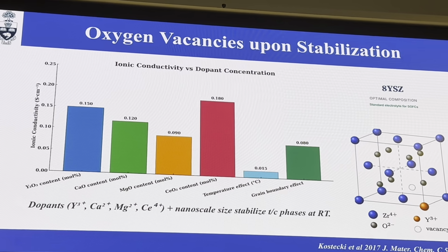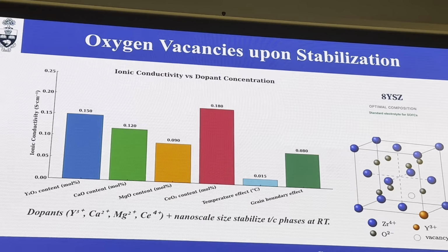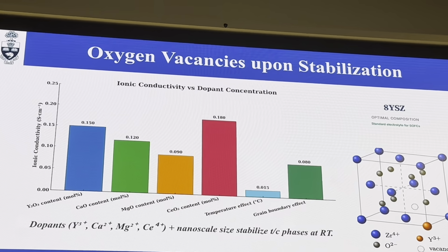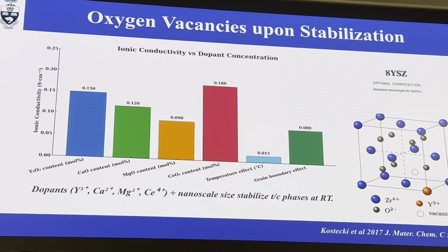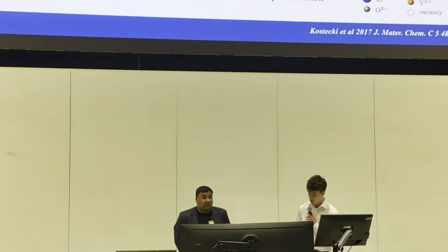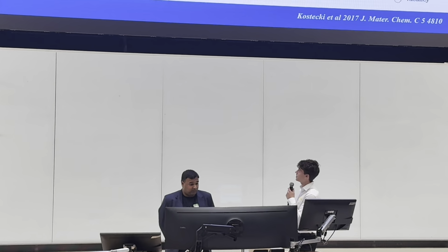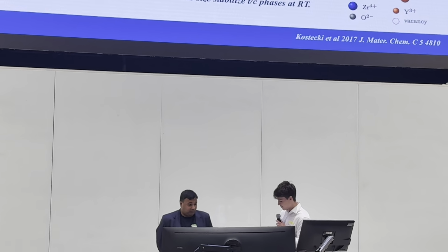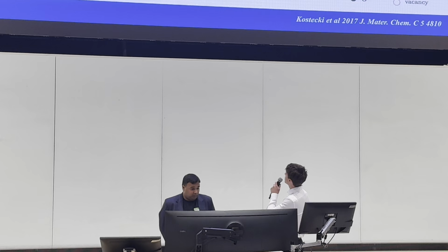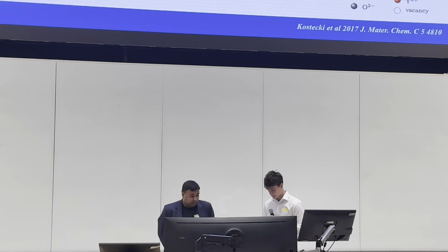Now, these vacancies are not just useless defects, rather they are crucial to zirconia's functionality. They enable oxygen ions to migrate through the lattice, which explains why stabilized zirconia shows much higher ionic conductivity. If you take a look at the bar chart on the left, doping zirconia provides about an order of magnitude higher ionic conductivity than pure zirconia alone, especially with raising temperature.